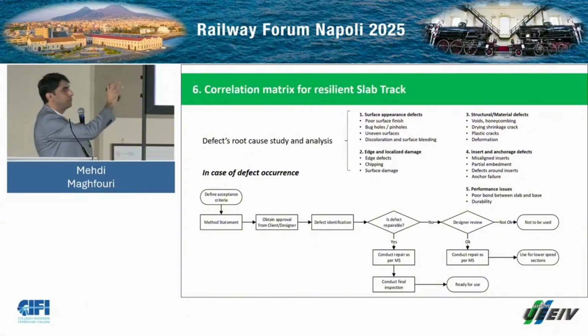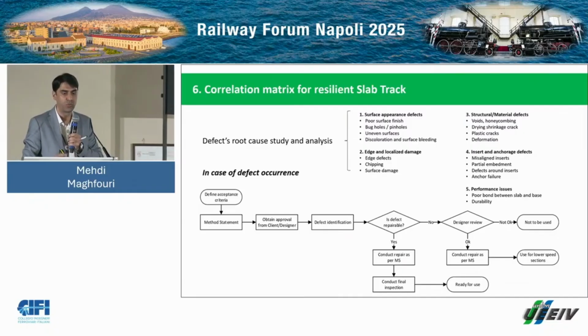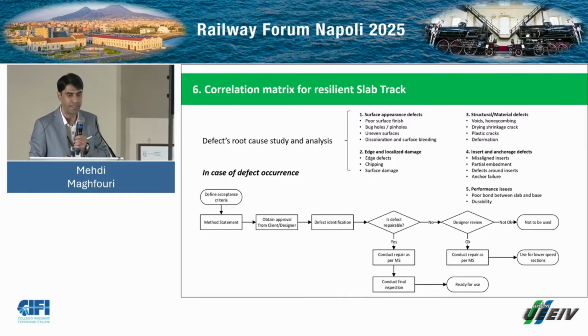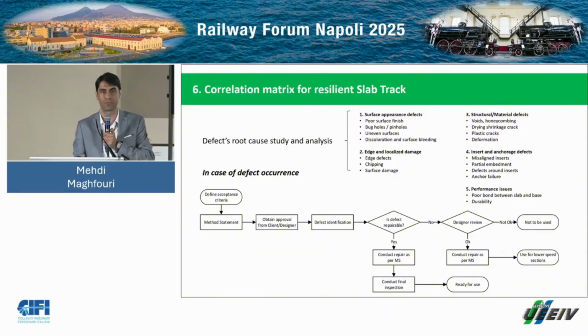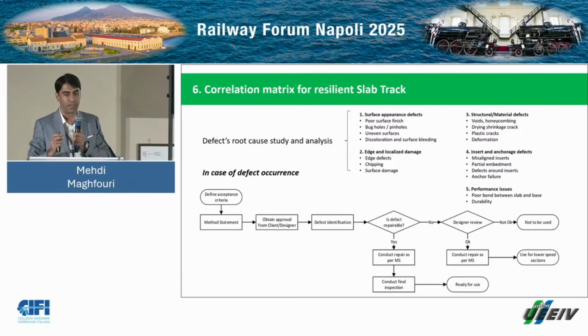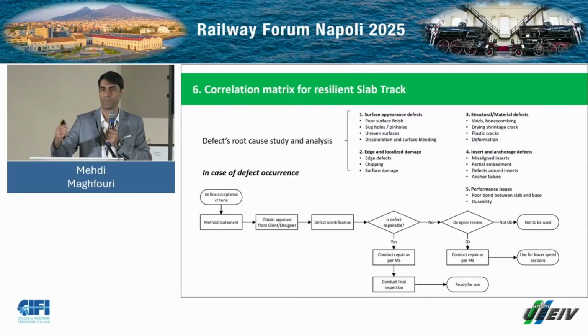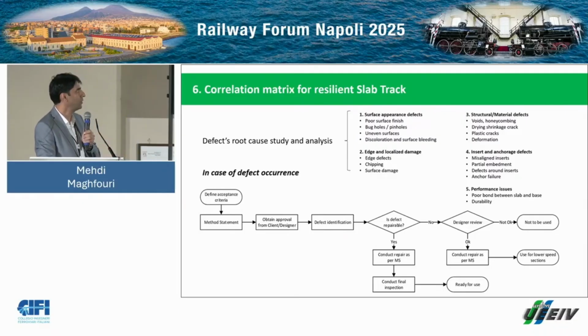So I already categorized the defects. First, we have to study the root cause and do the analysis. Once we know them, in case a defect happens, the first thing is to define the acceptance criteria and then come up with a method statement and obtain approval from the designer or the client. Then, if the defect is repairable, we can do the repairing and then conduct the final inspection, and the slab would be ready to use. If not, then a designer review must come into the picture, and if it's okay, then we can do the repairing and use that particular slab for sections with the lowest speed. If not okay, then of course the slab would be rejected.